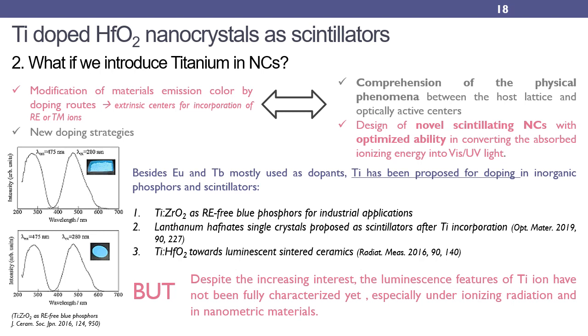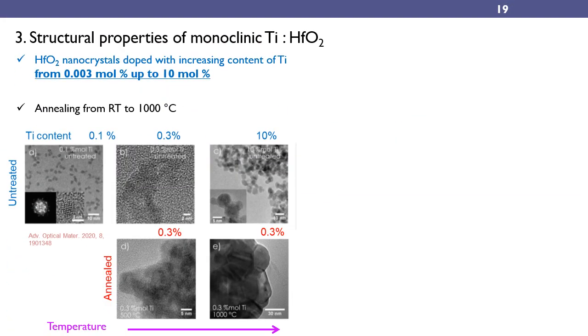Hafnium oxide nanocrystals are excellent hosts for titanium, since these ions can be naturally incorporated in the lattice, and it gives rise to an intense luminescence even at very low concentration. Here I present the results obtained for hafnia doped with titanium. Hafnium nanocrystals have been prepared and doped with increasing concentration of titanium from 0.003% up to 10%, and then a thermal treatment up to 1000 Celsius degrees has been performed.